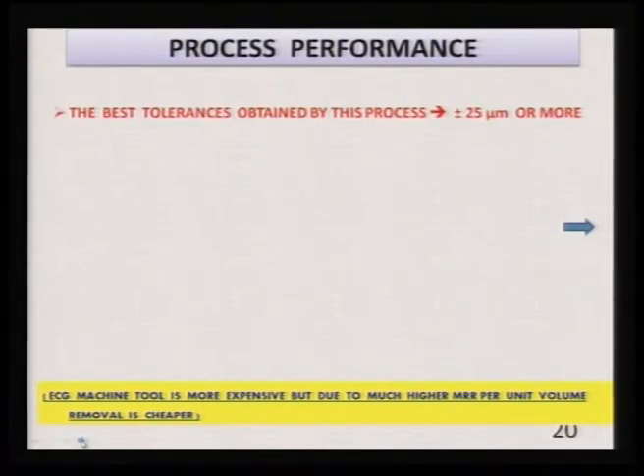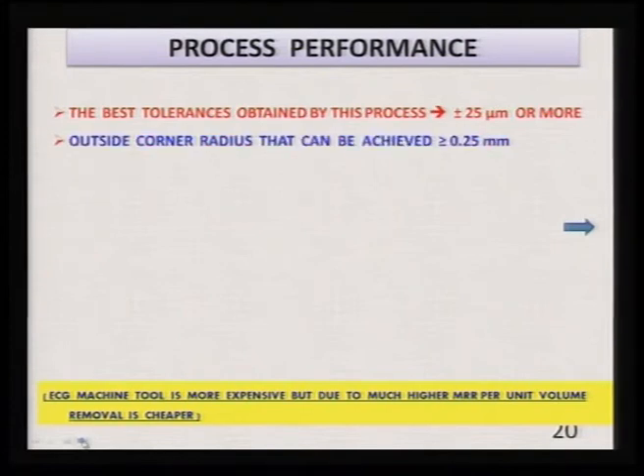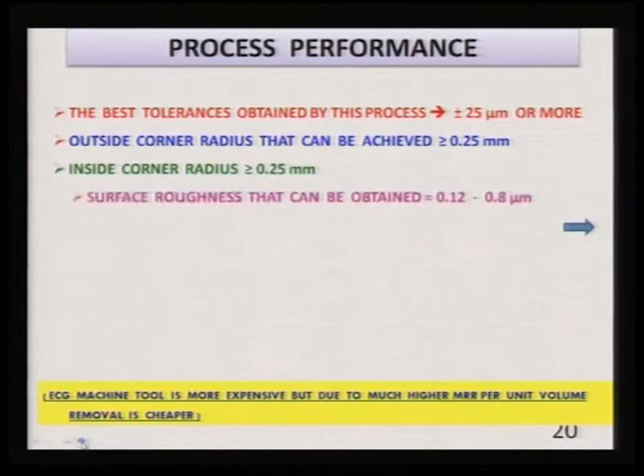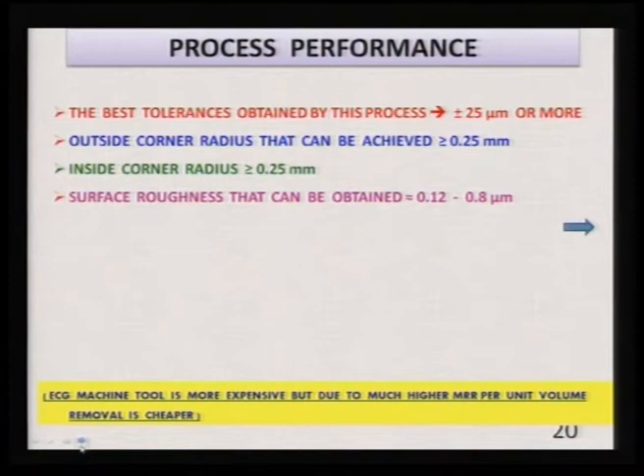Process performance continues. The best tolerances that can be obtained by this electrochemical grinding process are within plus minus 25 micron or more. Outside corner radius that can be achieved by electrochemical grinding is greater than or equal to 0.25 millimeter, that is 250 micron. Inside corner radius that can be achieved is again the same, greater than or equal to 0.25 millimeter. Surface roughness that can be obtained is approximately 0.1 to 0.8 micron, it lies in this particular range.